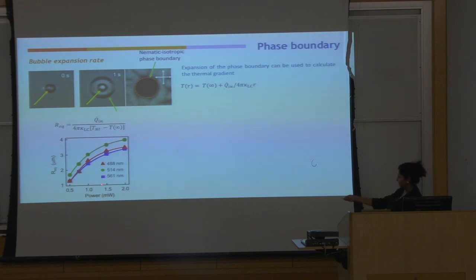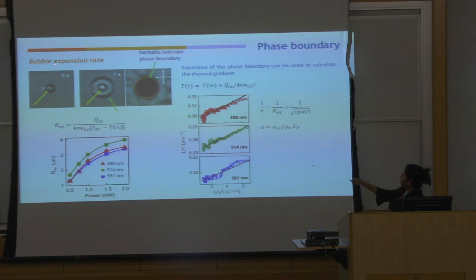That is experimental. We can also rework this to come up with this equation here, where we plot R and we incorporate the equilibrium distance here, the radius that we can measure in here, where alpha is just this ratio of physical parameters of the liquid crystal. This is density, this is specific heat. And we can measure with the high-speed camera, we measure as this bubble expands. So we are plotting the bubble radius.